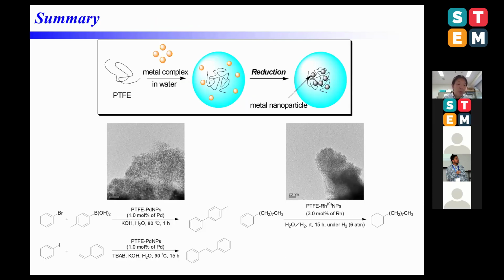In summary, we confirmed that PTFE can be used as a support for palladium and rhodium metal nanoparticles, and these nanoparticles show high catalytic activity and reusability for the Suzuki coupling reaction, Heck reaction, and alkene hydrogenation.